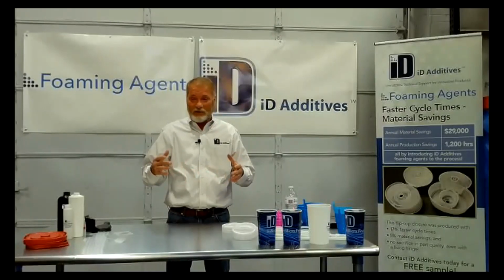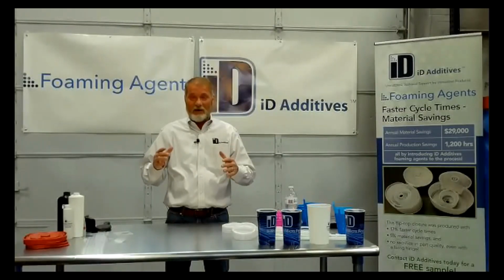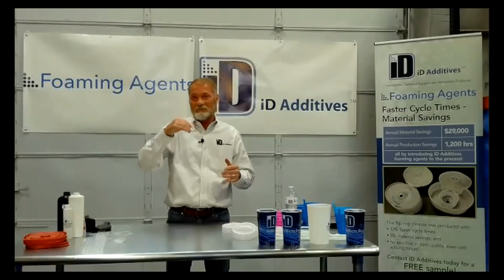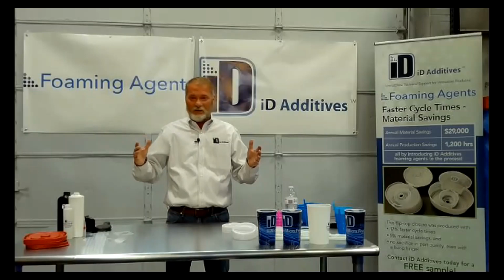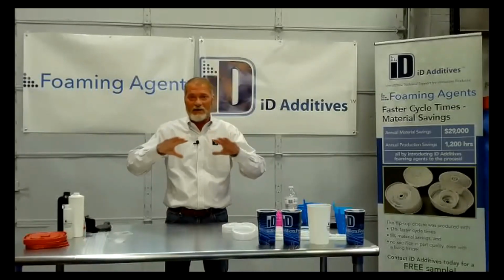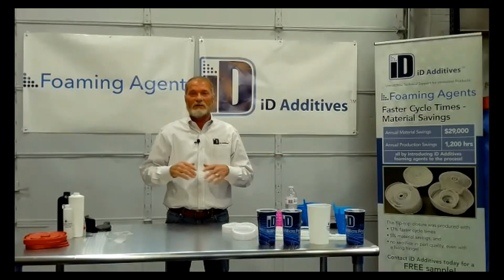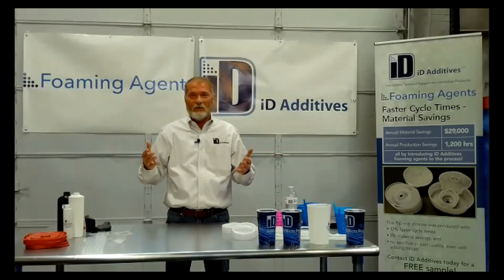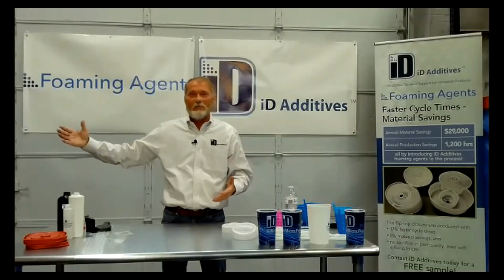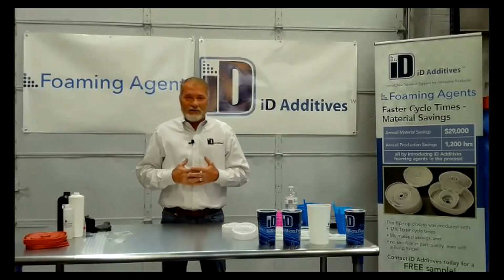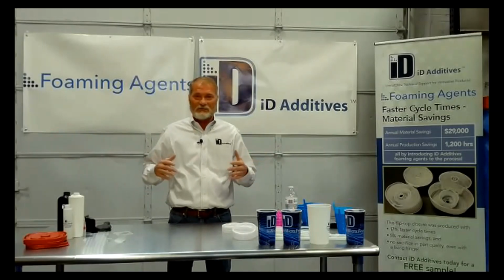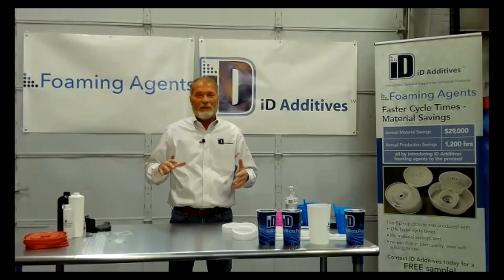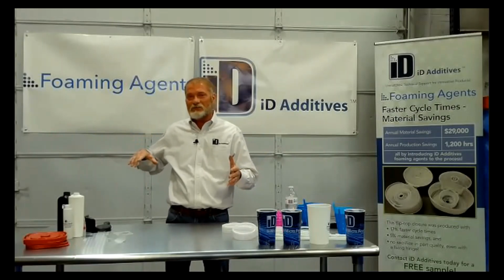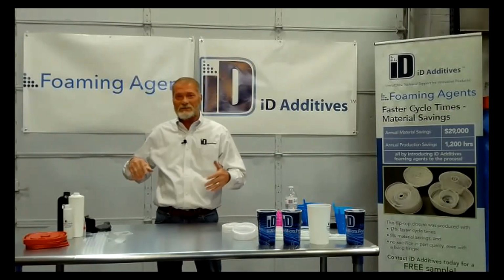And when you're at 1200, 1300 at 0.5, you'll end up being around 1,000, 900, maybe 800 psi, which means you've got the nitrogen down, your voids are not near going to be as bad, and that foam is really, I mean, you're adding over 60 cc's per gram of gas at 0.5%, which is almost a typical foaming agent at 1%. So you're adding a lot of endothermic foaming agent in there that's really going to do a good job. Plus, the endothermics change that viscosity of the material in the screw before it gets to the nitrogen valve.